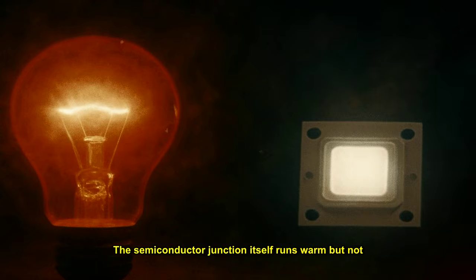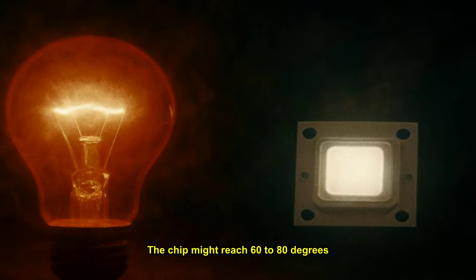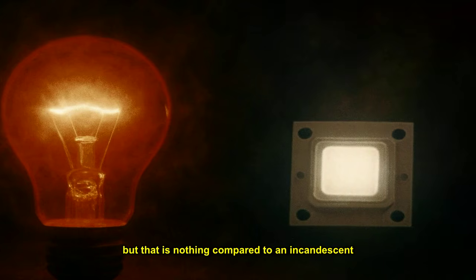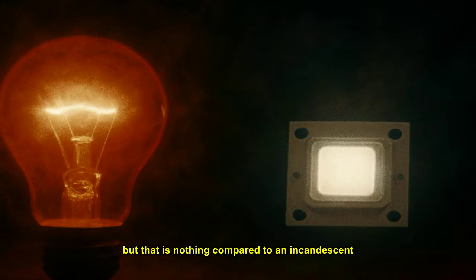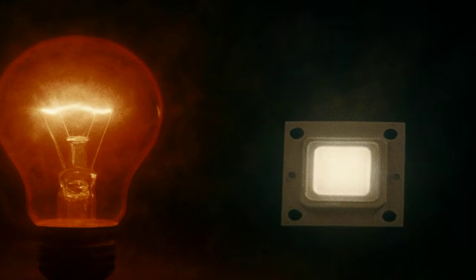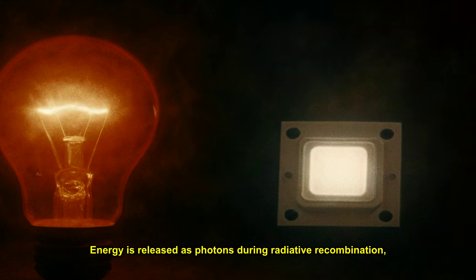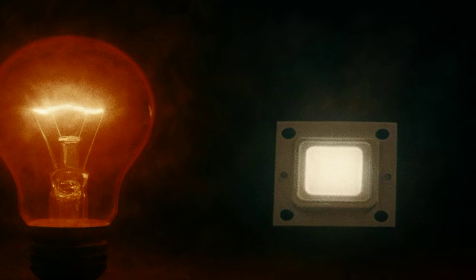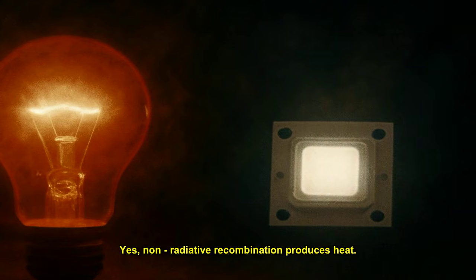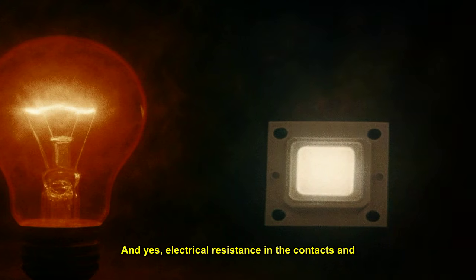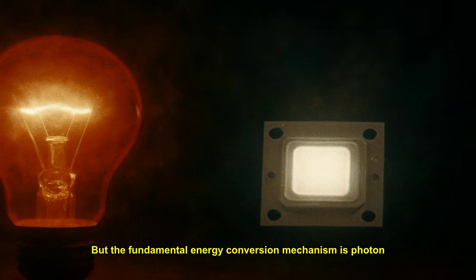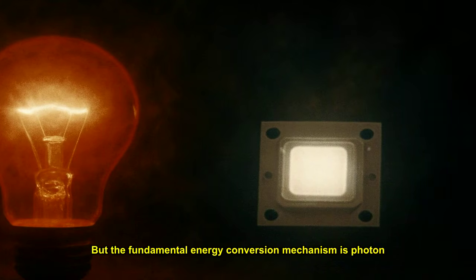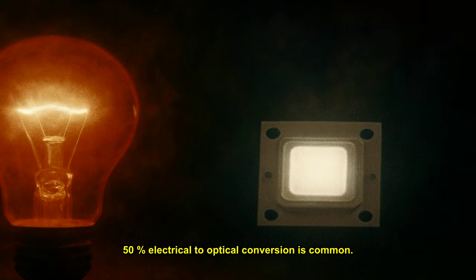The semiconductor junction itself runs warm but not hot. The chip might reach 60 to 80 degrees Celsius under high current, but that is nothing compared to an incandescent filament. The reason is quantum mechanical. Energy is released as photons during radiative recombination, not as bulk heating of the material. Yes, non-radiative recombination produces heat. And yes, electrical resistance in the contacts and wires produces some heat. But the fundamental energy conversion mechanism is photon emission, which does not require high temperature. This makes LEDs far more efficient. 50% electrical to optical conversion is common. The best lab devices exceed 70%.